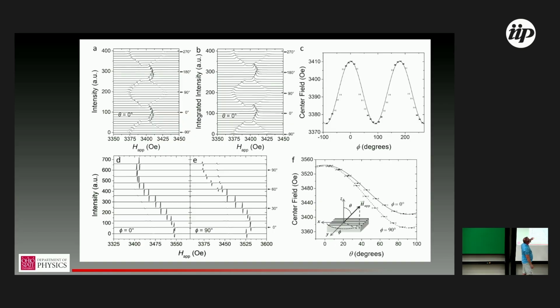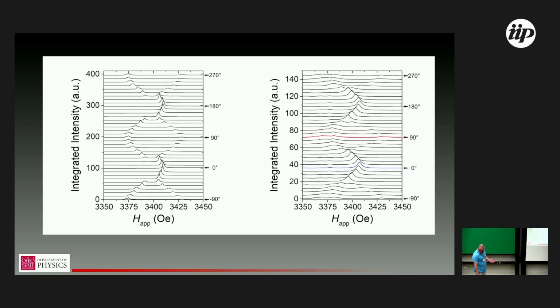So that's for the in-plane rotation. And then again, we have 2 different flavors of in-plane to out-of-plane. So you can come and land in-plane parallel to the wire or in-plane perpendicular to the wire. And so you can fit to each of these 3 plots. In the upper right is the fit to the in-plane, and the open circles indicate data that we've ignored in the fit because it gets close to this anti-crossing. So it's kind of distorting the angular variation. And then the 2 fits to the in-plane to out-of-plane down there. Again, we can extract all of the anisotropy parameters for this structure phenomenologically because it's a complex shape.